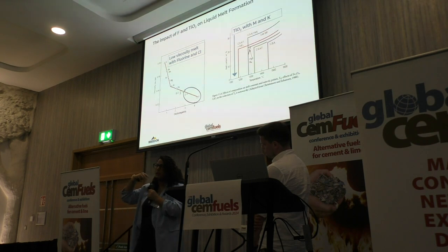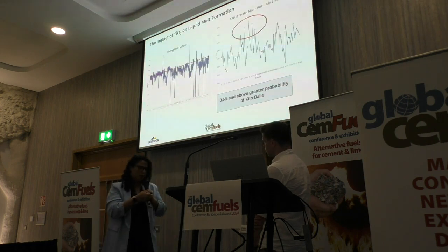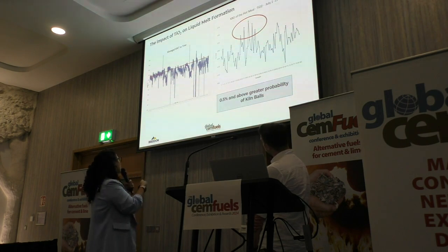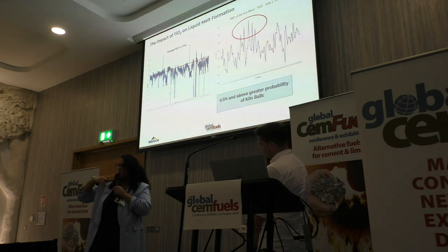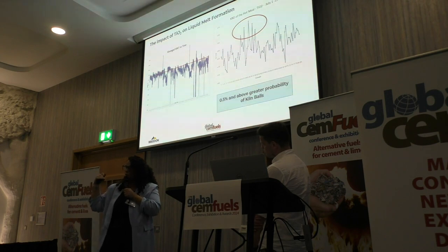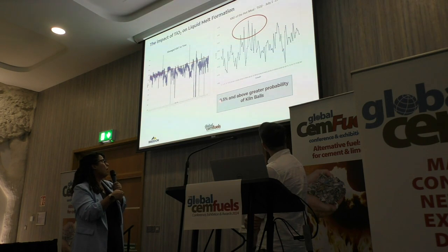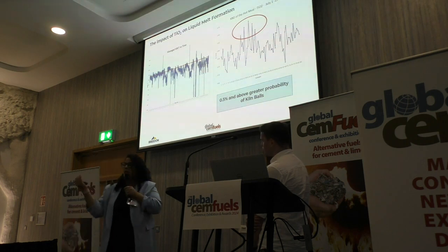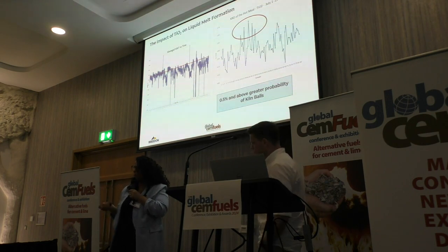So when we could improve the combustion, we reduce these build-ups formation. And also, the plant could, as you can see in here, pretty much operate. Of course, it's a normal temperature for the kiln backend, but from time to time it goes a little bit above. And with this titanium, this is enough for them to start to have this liquid phase a little bit out of place, which is the condition. And we could find a guidance, like a limit. So every time they go a bit above this 0.5 for the titanium, then combined with the build-ups, it will create the kiln balls.